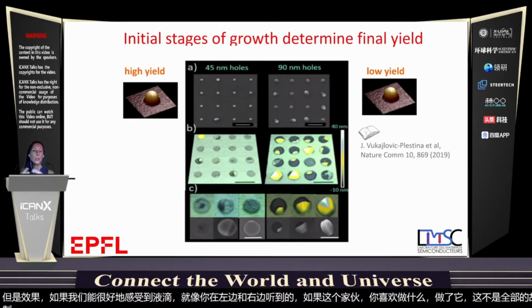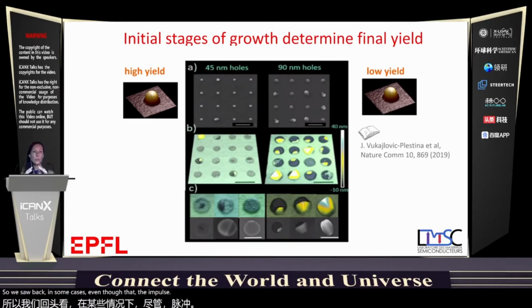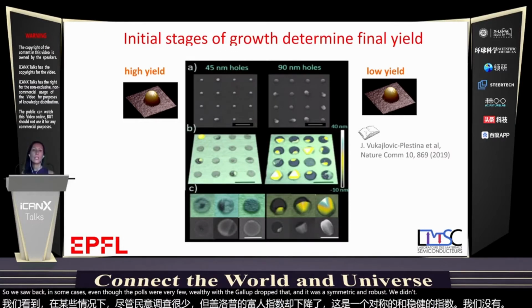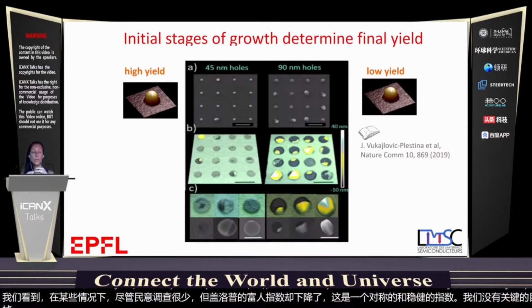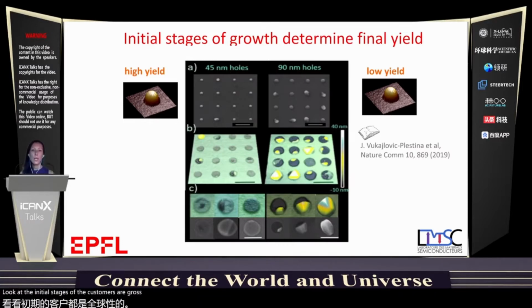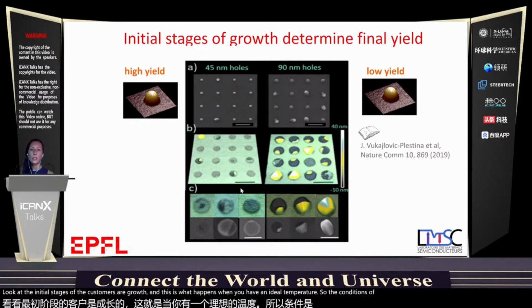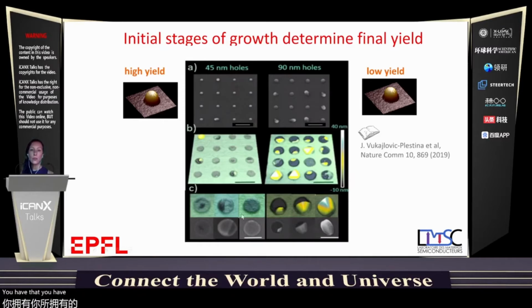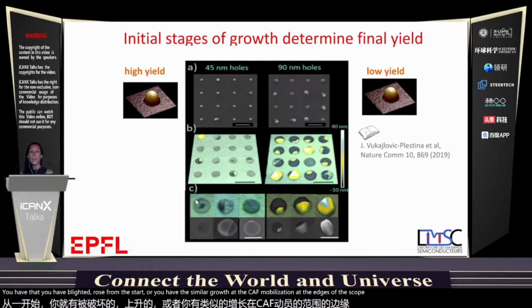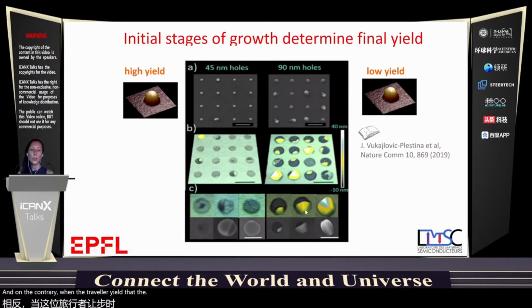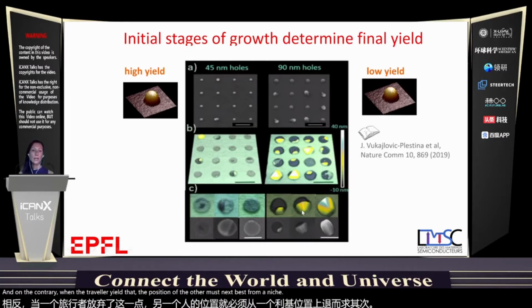So we saw that in some cases, even though the holes were very well filled with the gallium droplet and it was symmetric and all this, we didn't have vertical growth. So we looked again at the initial stages. We removed the gallium droplet and looked at the initial stages of the gallium arsenide growth. And this is what happens when you have high yield and low yield. In the conditions of high yield, you have planar growth from the start, or you have this circular growth with nucleation at the edges of the hole. On the contrary, when you have a low yield, the nucleation of the gallium arsenide starts from an edge. And this is what fills the wire on the side. So it was very strange.